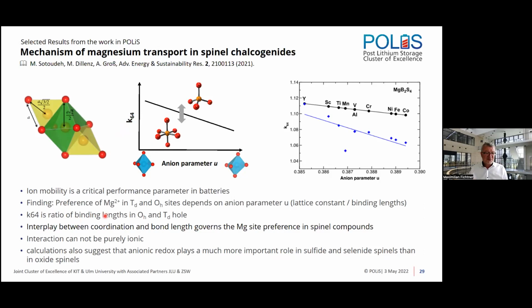This is a parameter which is influenced by the lattice constant and the binding length in the different environments. And this is something you see here. This is a ratio of binding length in octahedral and tetrahedral hole, where an ion would have to go through when it migrates. And this interplay between the coordination and the bond length governs the magnesium site preference in spinel compounds, and it leads to the conclusion, an outcome of their study, that the interaction cannot be purely ionic. Now, this is not necessarily new. That there are influences from the anions and that there are soft anions and hard ions, which can influence the migration, was known before, but it has not been really quantified in terms of a descriptor. The calculations in that case also suggest that anionic redox plays a more important role in sulfide and selenide spinels than in oxide spinels.